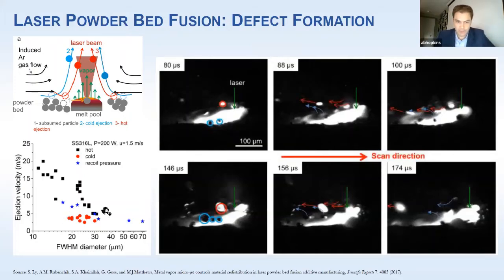And that's different from the ejecta. These hot particles here are just little molten masses that are sprayed from the melt pool itself, for similar reasons. So you have a lot of ejecta, is the point, and you can form defects with all this material going in and out of the melt pool. These are different types of defect formation. So you need to figure out how to make this process repeatable. It's complicated enough that this is not a simple problem, is the main point I'm making.